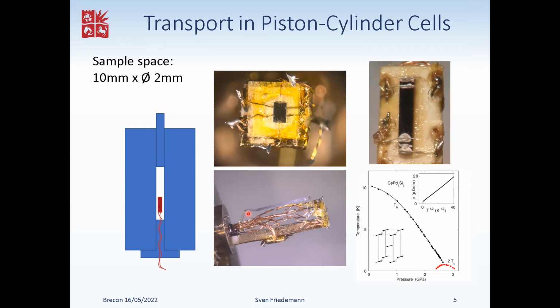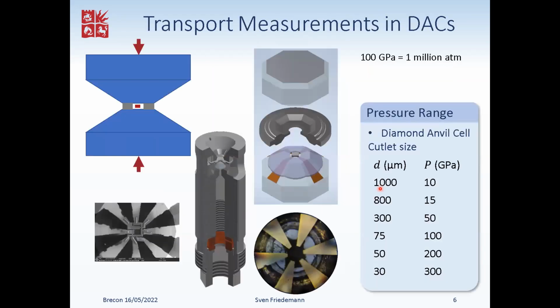Many secondary pressure gauges are available at the highest pressures. In diamond anvil cells, we often place a tiny bit of ruby. There's a chip of ruby right underneath this cursor, which you can shine a green laser or some high energy laser on to excite the fluorescence, and record the fluorescence. It's in red, of course, because ruby is red. And that shifts as a function of pressure that has been calibrated before. So we can this way figure out the pressure.